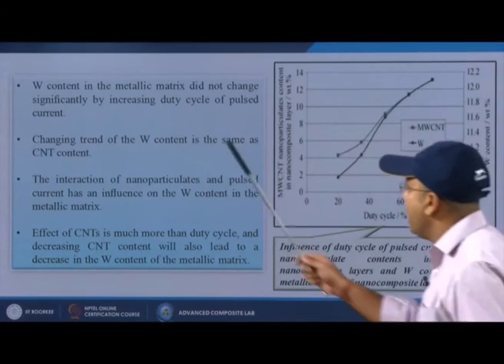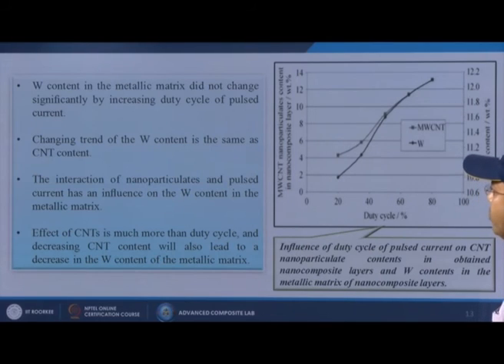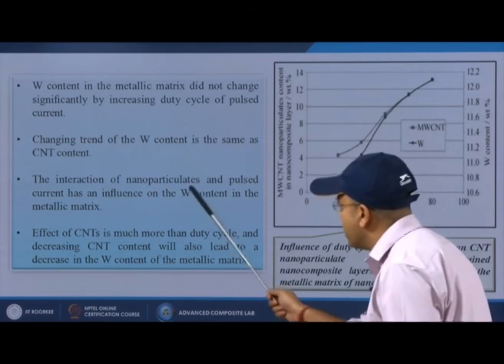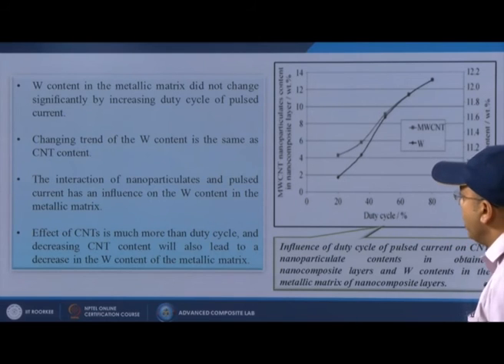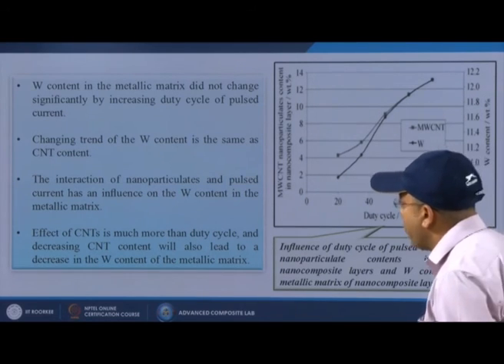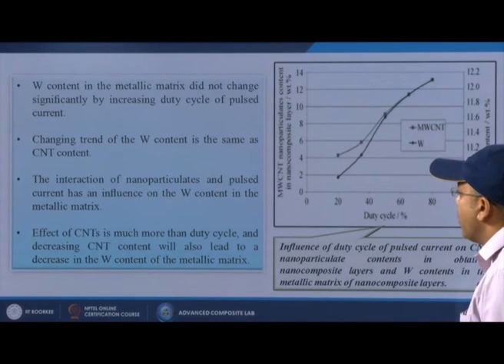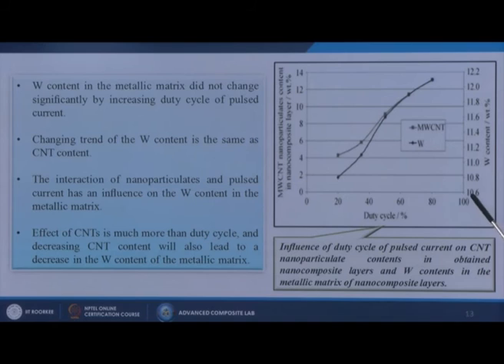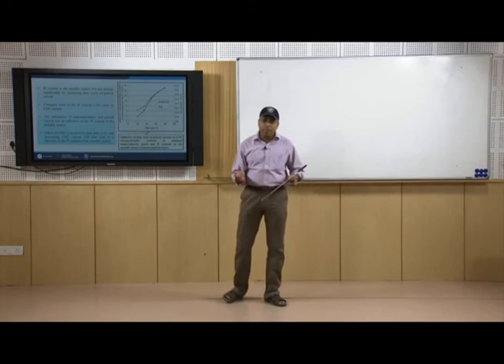So, tungsten content in the metallic matrix did not change significantly by increasing duty cycle of pulsed current. The changing trend of the tungsten content is the same as CNT content. In this particular case, the interaction of nanoparticulates and pulsed current has an influence on the tungsten content in the metallic matrix. The effect of carbon nanotubes is much more than duty cycle, and decreasing carbon nanotube content will also lead to a decrease in the tungsten content of the metallic matrix. So, from this figure we can get the influence of duty cycle of pulsed current on carbon nanotube nanoparticulate contents in the obtained nanocomposite layers and tungsten contents in the metallic matrix of the nanocomposite layers. So, that is a mixture, or maybe that is the hybrid composites kind of thing.